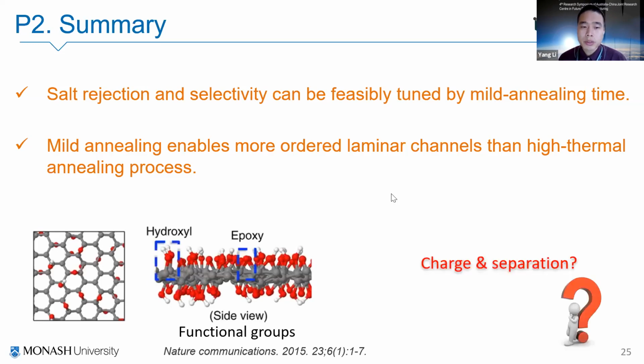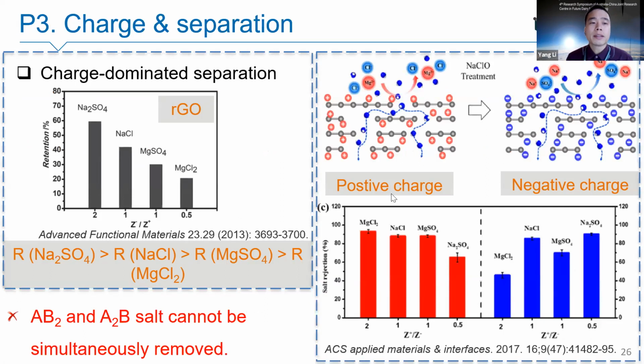GO actually has various hydroxyl, epoxyl, and carboxyl functional groups, and the charge is very important in nanofiltration. So the third project we conducted is on the charge and separation relationships. From the literature review, we already know that charge-dominant separation is very common in nanofiltration for the reduced RGO membrane. Generally, we know the salt separation follows the sequence of salt rejection. Sodium sulfate has the highest salt rejection, but magnesium chloride is the least rejected salt when we use RGO membranes. So the AB2 or A2B salt behaves quite differently.